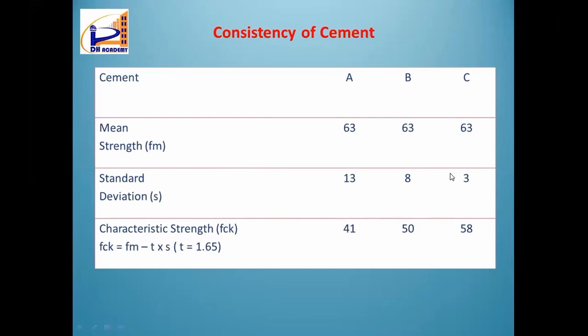Now for design calculation, we are not directly taking that mean strength value. We are taking the characteristic strength value. That means FCK. FCK is equal to Fm minus T into S. So in case T is 1.65 and S, suppose in case of cement A it is 13, the characteristic strength is only 41. But whereas in case of cement C, since the value of standard deviation is only 3, we are deducting a small quantity from Fm. So that is the reason why FCK came as 58 megapascal.